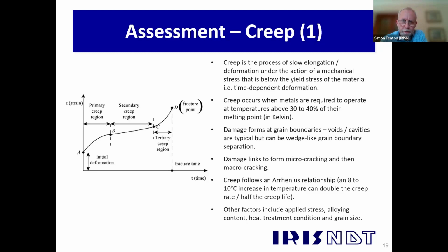The creep process follows an Arrhenius relationship. So as a rule of thumb, for every 8 to 10 degrees C increase in temperature, you can double the creep rate, half the creep life. So controlling temperature on power plants is a very, very key thing. The other factors, as you're probably aware, are the stress that you apply, the alloying content, the heat treatment condition, and the grain size is also important.